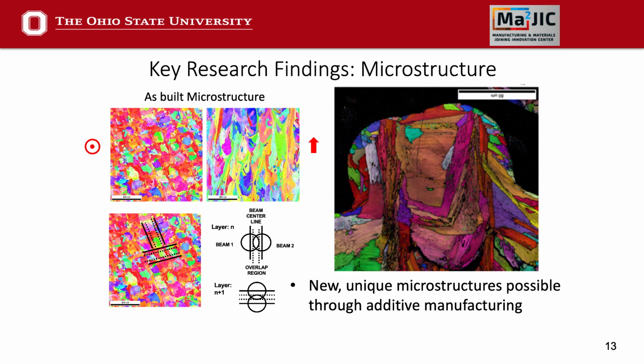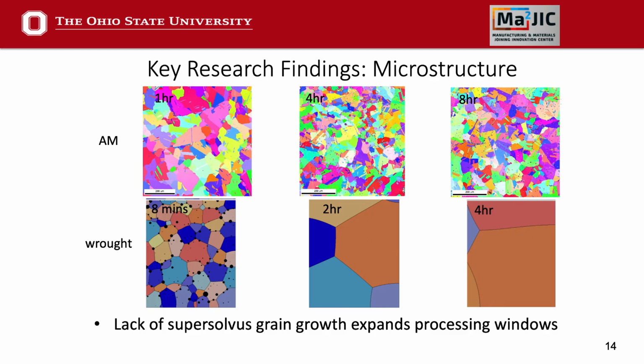So we're able to do these single track and double track experiments where we can see how this specific microstructure develops over time and why we only see it in certain conditions and not in other processing conditions. We also found, which is very interesting, in the supersolvus heat treat condition, as I mentioned, in the wrought version of this alloy, you experience very rapid grain growth in the supersolvus condition. We found it very interesting that we don't see this in the supersolvus condition. Looking at even up to an 8-hour hold time, we don't see grain growth. It opens up a whole processing window that we don't see in traditional manufacturing.